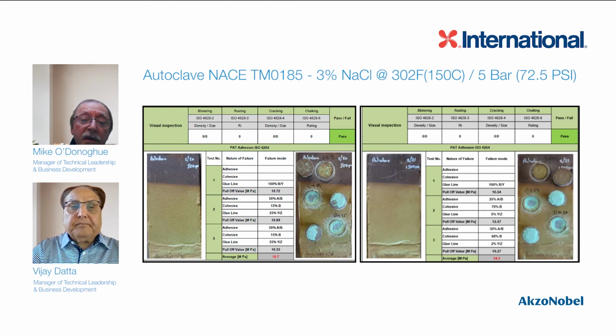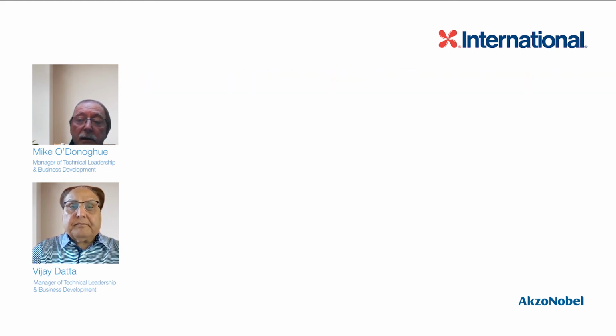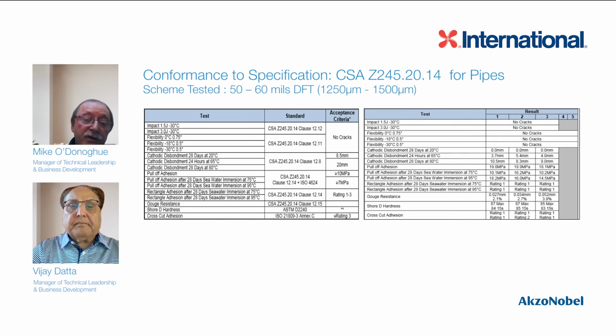I mentioned a few moments ago the CD testing, didn't I, Vijay? And not only the CD testing is examined, but we look for the flexibility of the coating at temperatures down to -30, the impact resistance down to -30, with Enviroline 376 conforming to Z245.20.14.